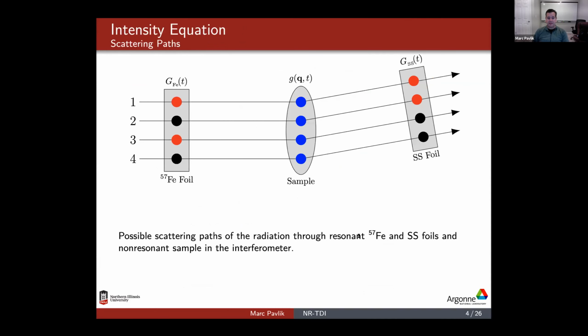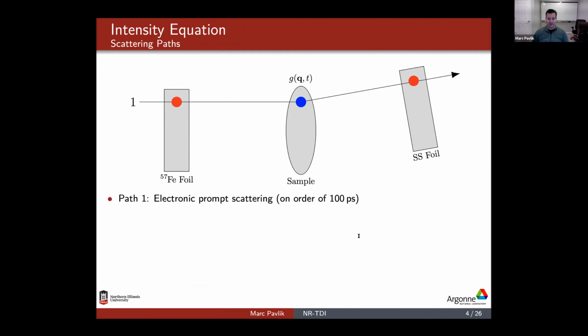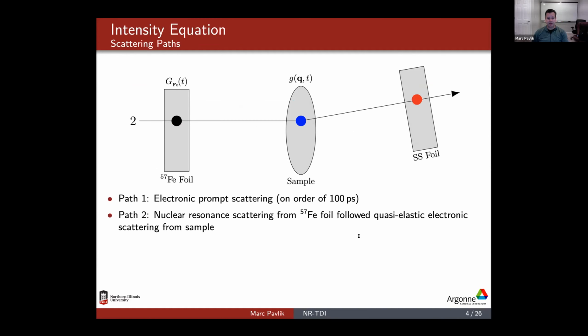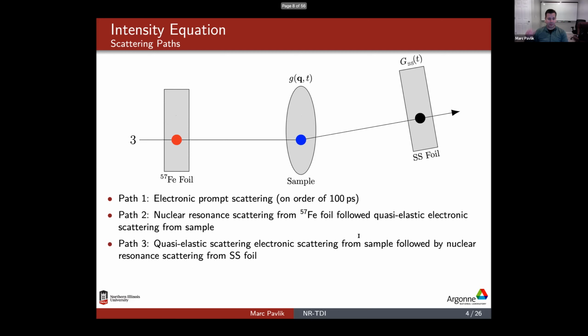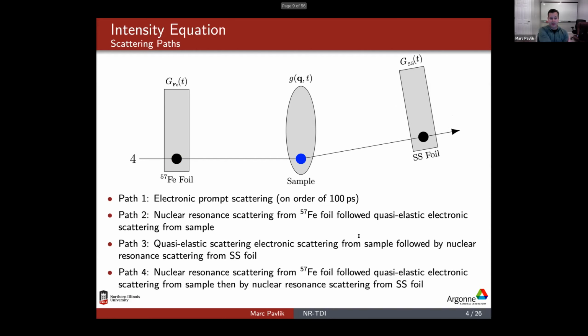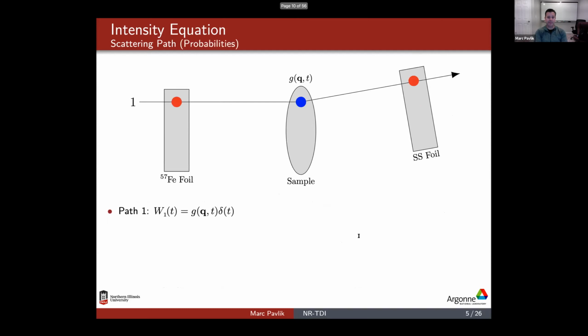So there are 4 possible scattering probabilities or paths through the foils and the sample. The first path is just electron scattering from the prompt. The second path is a nuclear resonant scattering from the foil, followed by the quasi-elastic scattering from our sample. The third path is the quasi-elastic scattering from the sample and the nuclear resonant scattering from the stainless steel foil. And the fourth path is the nuclear resonance scattering from the iron foil, followed by the quasi-elastic scattering from the sample and nuclear resonance scattering from the stainless steel foil.